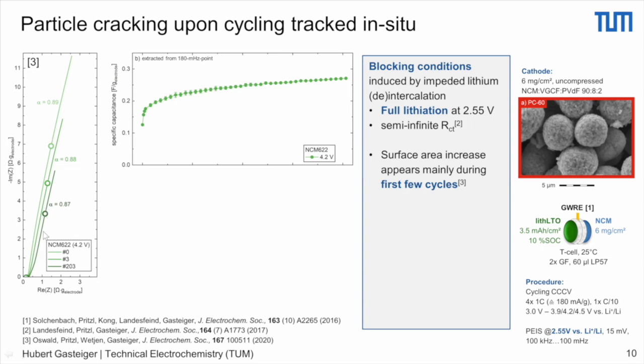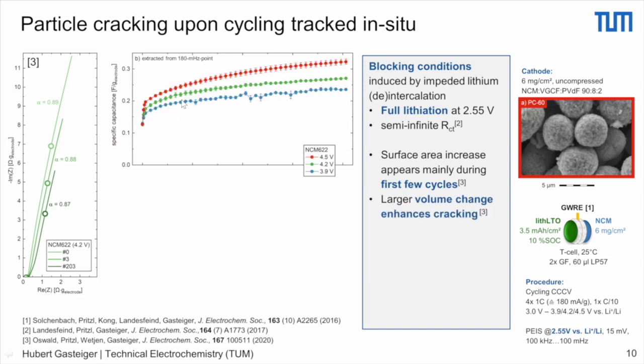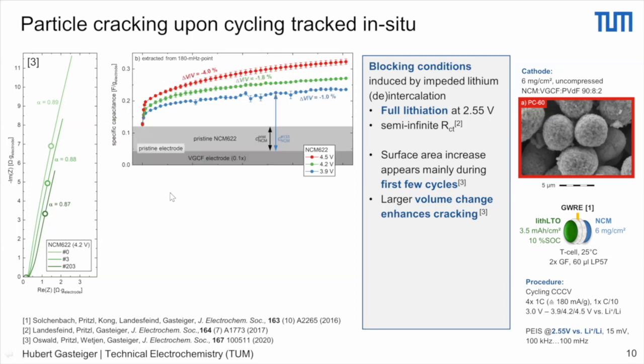What we can see is a change in capacitance. This is just here marked by the 180 millihertz frequency point. And when we look over the cycling, then what we see is that depending on the cutoff potential, 3.9 volts versus lithium, 4.1 or 4.2 or 4.5, we get a stronger increase in the capacitance. So again, as I said before, we have to subtract the contribution from the pristine electrode. And so the ratio of the pristine electrode minus the carbon contribution, which is this part here, and the signal afterwards, that is our increase in active surface area, which we deduce from these capacitance measurements.